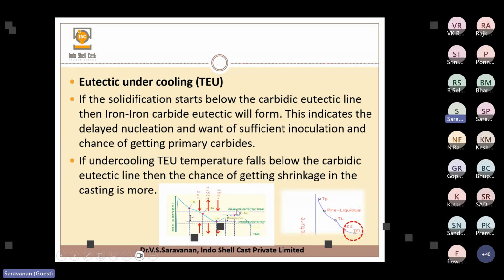So here this is the carbide eutectic line. This is TEU. If the solidification goes below this, then there are chances of getting carbides here, and sometimes even porosity, because the nucleation potential is not good. So if the undercooling TEU temperature falls below the carbide eutectic line, then there are chances of getting shrinkage also.